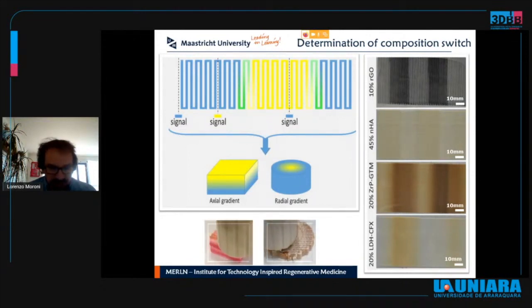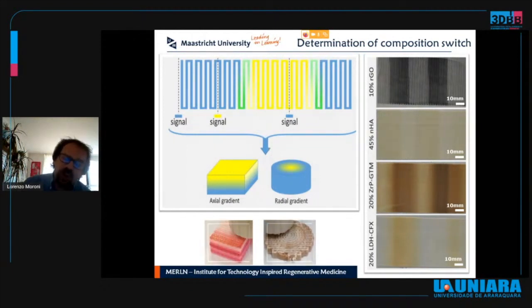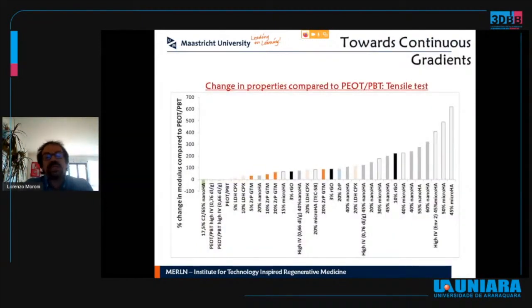And you see here on the left an example with just a food dye, so that's where the scaffold changes from the more whitish color of the original polymer we used into a more pinkish color where the highest concentration of the food dye is present. And on the right side, a real biological case where we have added inorganic compounds containing antibiotics, and that's why you see the brownish color, which is not the polymer being burned, but it's actually the color of the inorganic compounds that we have included into the blending system while printing.